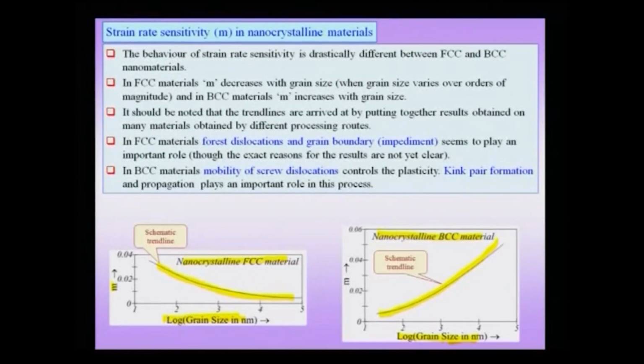So, the effects are exactly opposite when you are talking about nanocrystalline materials and the important parameter of strain rate sensitivity, and that implies that the behavior of strain rate sensitivity is drastically different between FCC and BCC materials. There is some understanding which we will see very soon, but the complete picture is not yet out. In FCC material, m decreases with grain size, and this grain size variation is over a few orders of magnitude, and in BCC material, m increases with grain size, unlike in the FCC materials.